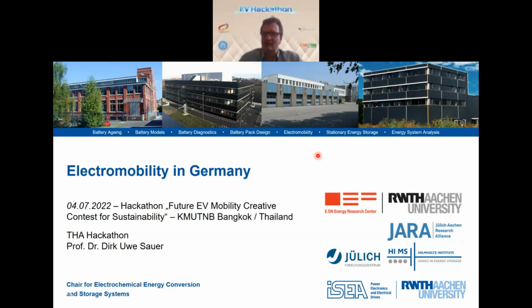Probably not in the stationary sector, because they need much higher cycle lifetime, and we don't have high cycle lifetimes with pure nickel or manganese-based systems yet. The other alternative is lithium iron phosphate, which goes beyond any nickel, manganese and cobalt, but at lower performance regarding the energy density. And then more or less the only thing I see until the end of the coming decade is sodium instead of lithium. CATL has announced to come this year with products, and there should be some prototypes somewhere, but I haven't had them in my lab yet personally. But this will be an option, at least in the cheaper cars, not in the highest performance cars because of lower energy densities.